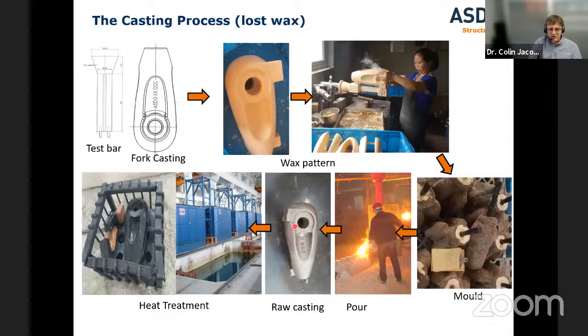Now, this stage is critical. From a raw casting, it has to go to heat treatment, else you will not get the required properties. Generally, at this stage, it may have the strength, but it will not have the ductility. So going into the ovens here, and from the ovens, they go into the quench pool. This provides the quenched and tempered properties. What's important here is that this test bar is heat treated in these ovens at the same time as your casting, your product. Very important that occurs.